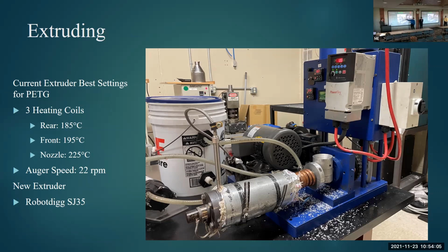Then, as we have mentioned for our optimal settings so far, we have the rear heater at 185, the front heater at 195, and finally the nozzle at 225 C. And we actually have the melting point at just the extruder because we don't want it melting back in the barrel and potentially clogging it. And also we don't want the flow rate too high. Otherwise, when it escapes from the nozzle, it will create voiding within the material that's extruded. And then the speed of the auger is at 22 RPM.